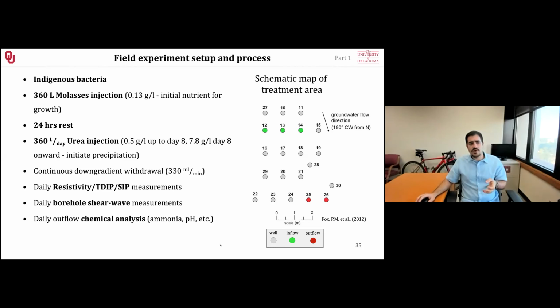At the same time, we were measuring resistivity, time domain IP, and spectral IP, which will give us complex conductivity. So we had every geophysical method, geoelectrical method over there. Additionally, we had the shear wave velocity measurements in the boreholes that were provided to us. So we had the ground truthing ability with the shear wave velocity. And we also collected all the chemicals in the effluent to analyze a lot of different things such as ammonia, pH, conductivity, and so on.